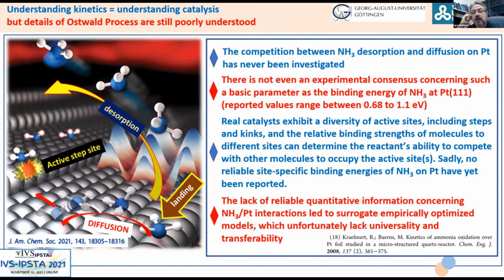and you can imagine that such differences can change the kinetic picture completely. Beyond that, real catalysts exhibit often, and always actually, a diversity of active sites: steps, kinks, and so on. However, there are no reports in the literature of site-specific binding energies of ammonia on platinum. And due to this lack of reliable quantitative information, we are often forced to rely on so-called surrogate, empirically optimized models, sometimes even with unphysical parameters optimized for a certain range of interest.